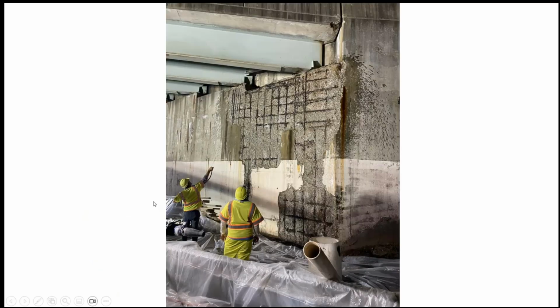Now here is the abutment that we fixed. This was supposed to be the experiment, but as you can see, it's a very large area, and you needed lots of material. But we did not. I think we took enough material to make about 40 cubic feet of UHPC, and you needed to do both abutments, all the area. You needed at least about 100 cubic feet. So a little less than 4 cubic yards of UHPC you needed, but we didn't have that much material really. So they did sandblast it, they did expose it.